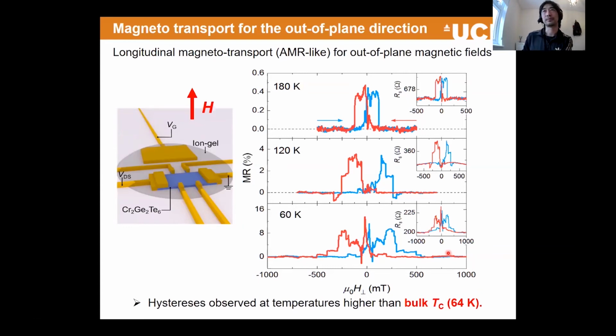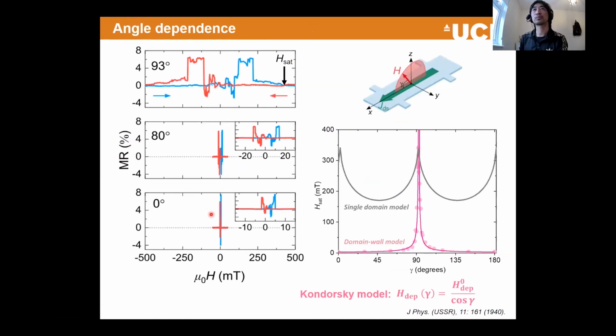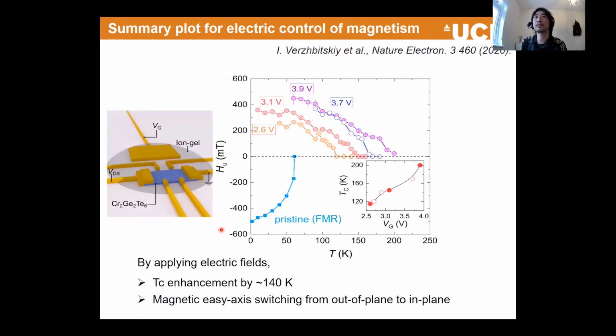So from that, what we can tell is that already Curie temperature is enhanced by more than 100 Kelvin by the gate application. And this is just an out of plane scan, and repeating the same experiment by changing it out of plane. Again, this is a bit more spintronic-y, but I just want to tell that we can see a large hysteresis, and when you bring this moment out of plane, so moment in plane here, this angle is 0, then we can see that this is the in plane favorable material. Okay, so then we just plot this.